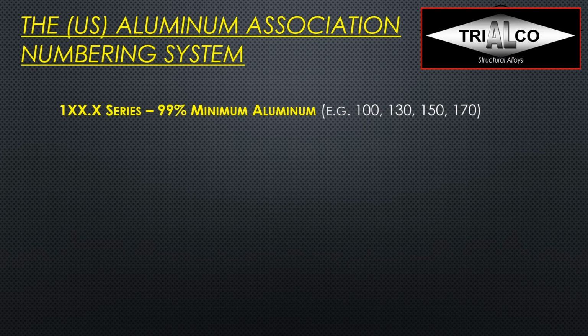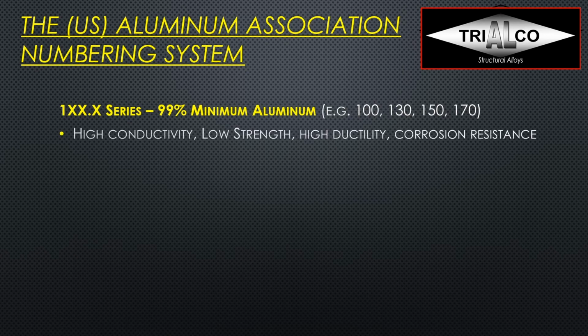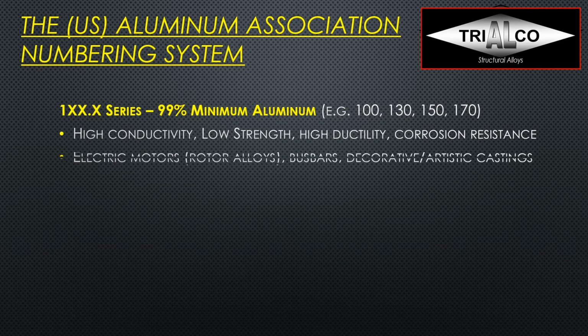So now let's have a look at the different series in our foundry alloys, and let's get started with the 100 series. As I said before, that's pretty much pure aluminum, so at least 99% minimum is aluminum. The typical representatives here are 100, 130, 150, and 170. And they all have one thing in common, pretty high conductivity. Of course, it's pure aluminum. There is no strengthening element in there, so they are low strength but very high ductility, and they're pretty corrosion resistant, just as pure aluminum is. And therefore, they are used primarily for electric motors. That's why we call them rotor alloys. They're also used for some bus bars, so electrical conductors, or decorative and artistic castings.